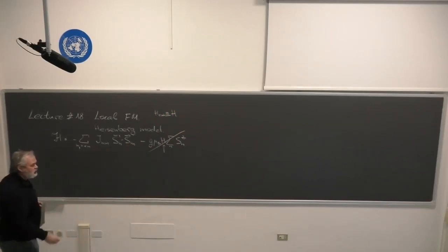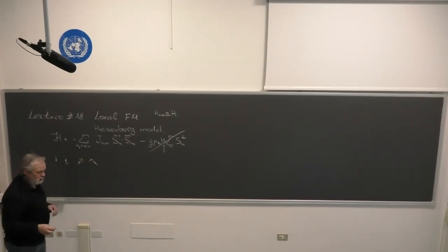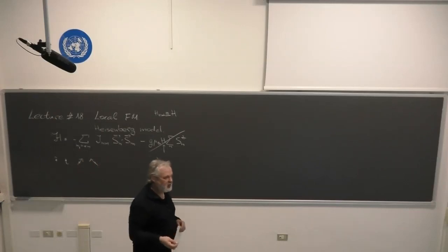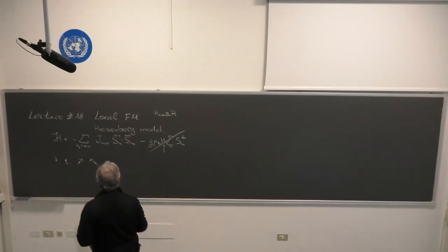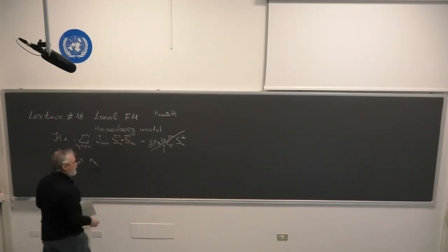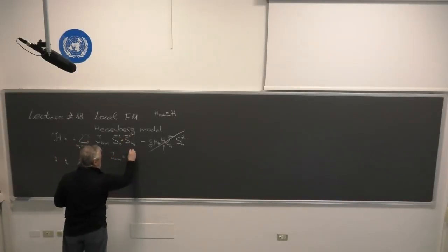So, what is it here? We consider a lattice of atoms whose D or F shell is not completely filled, and therefore, according to Hund's rule, there is a local spin associated with each atom in the lattice. And these spins are talking to each other through the interaction, which depends, of course, on the relative distance. And J_nm is J, which depends on the modulus of n minus m.